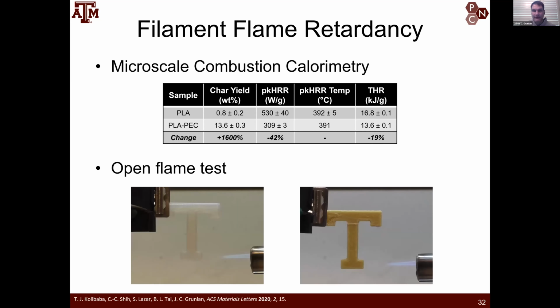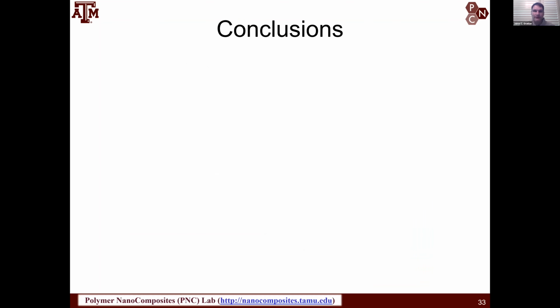And then in these videos, you'll have a chance to see the difference. So the PLA object, when a torch is held on it, melt drips and completely burns up, basically. But that melt dripping also spreads fire. You can see the other T, it just self-extinguishes immediately. When the torch is removed, there's no more burning. And you can see how it intumesced, it bubbled up where the flame touched the T. So truly, it worked very beautifully.